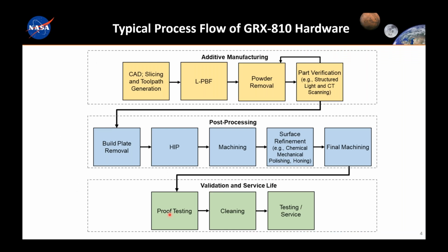So we've determined with the GRX 810 that it processes very similar to any of the standard nickel-based superalloys. And I think that's a very good thing. We're not seeing significant challenges in the post-processing by any means. So we follow a very typical flow that we would with any of the other powder bed fusion alloys. Starting with our early design, the actual build operation, the laser powder bed fusion build of, let's say, an injector or a nozzle. We go through extensive powder removal operations and verification of that powder removal, which is an iterative loop. And again, GRX 810, we've not seen any differences at all in that powder removal process.